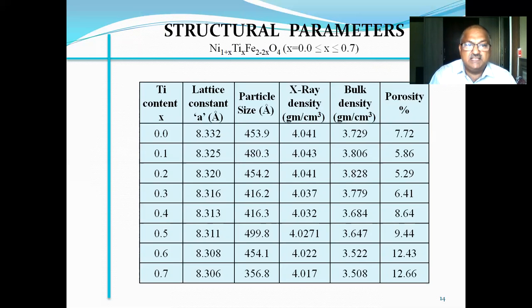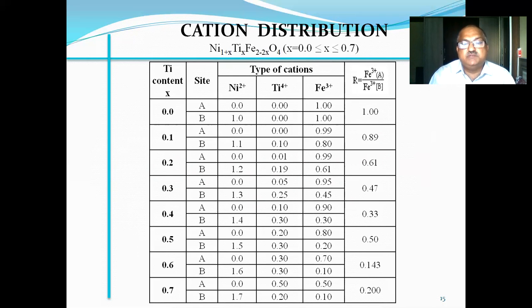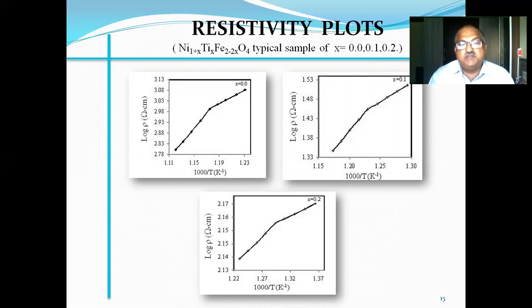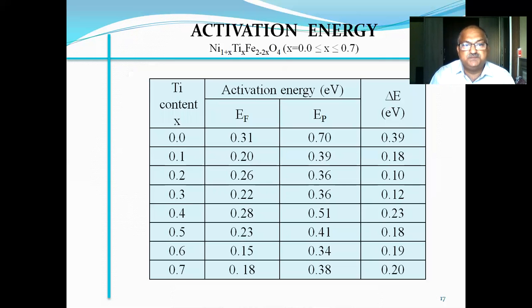Using that XRD data, I have calculated lattice constant, particle size, X-ray density, bulk density, and porosity. You observe that the lattice constant goes on decreasing as we increase the Ti4+ ion content. This is the cation distribution I have calculated using X-ray diffraction data. In the resistivity plots, you observe there are two parts separated by a kink, at which we get the activation energy, that is the transition temperature. The activation energy, you observe here, is very low, in the range of 0.18 to 0.31.